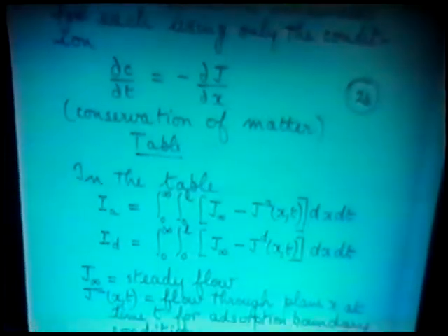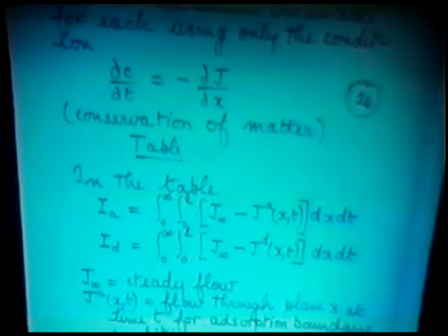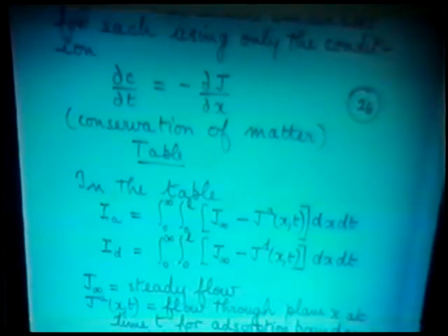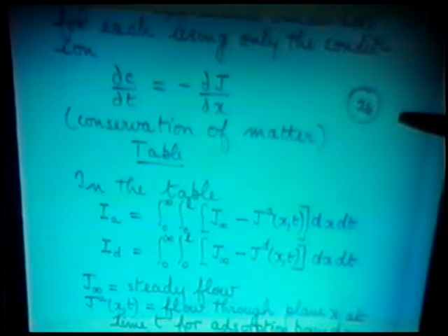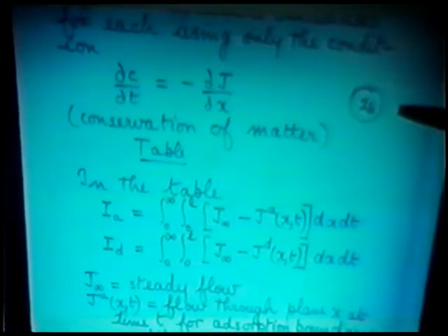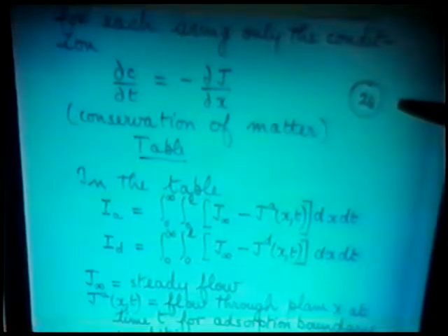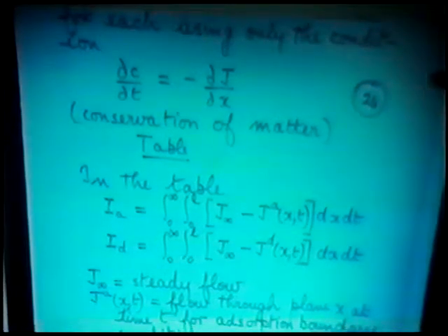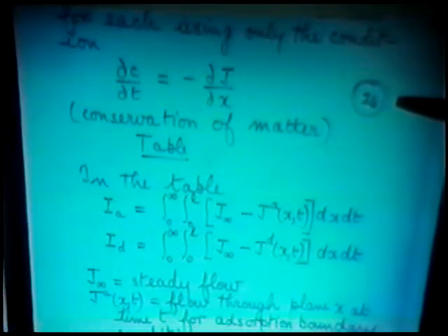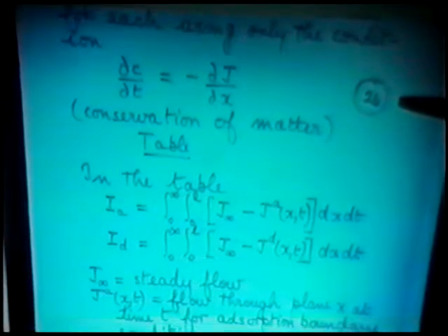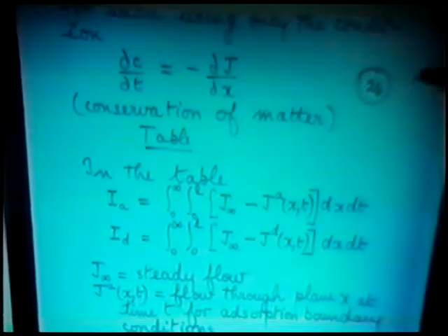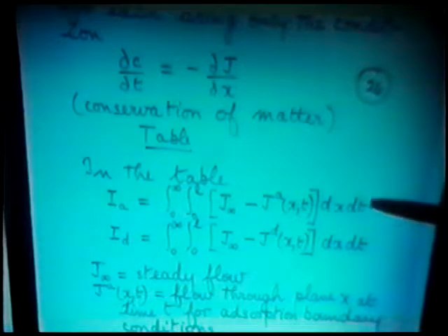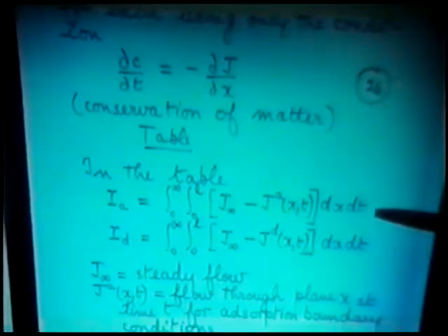Ash, myself and Edge were able to modify the Frisch method to derive all the time lags, not for such a limited case as diffusivity a function of concentration, but without reference to diffusivity at all. We found it possible to derive the expressions for all the time lags using only the continuity condition, which is simply conservation of matter. And I mentioned those integrals in the table. They have these values.